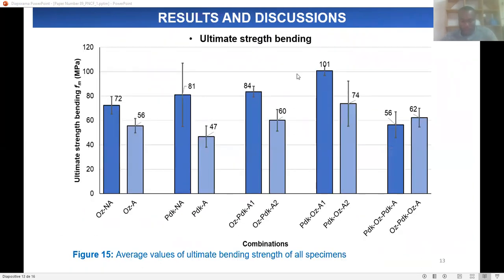Next, I will deal with the results and discussion. First, we have the average value of ultimate bending strength of all specimens. It is observed that the values found here are lower than those of the literature and that the strength of the lamella without finger joint is better than that of lamella with finger joint. For duo specimens, the Padouk-Ozigo combination in A1 configuration has a better strength, 101 megapascal. For trio, Ozigo-Padouk-Ozigo has better strength, 62 megapascal, than Padouk-Ozigo-Padouk, 56 megapascal.